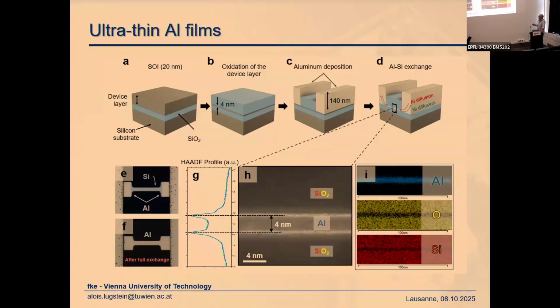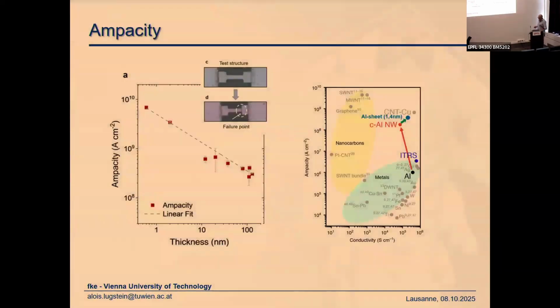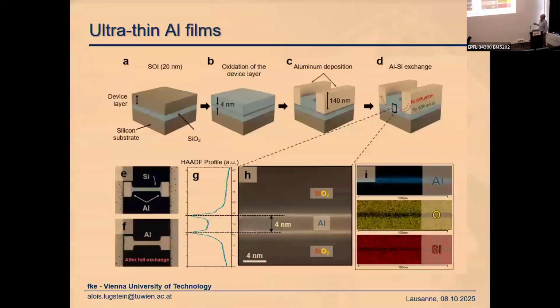So here you see the test structure, this bone-like structure. Here part of the structure is exchanged. This is still silicon. Here we have a fully exchanged sample. This is the cross-sectional view. So for this device, we have an aluminum sheet which is about 4 nanometers thick, which is also proven here by the EDX investigations. And by that, we can now, in a very similar way as we did it with the length of the segment, tune the thickness of this aluminum sheet by these oxidation steps.